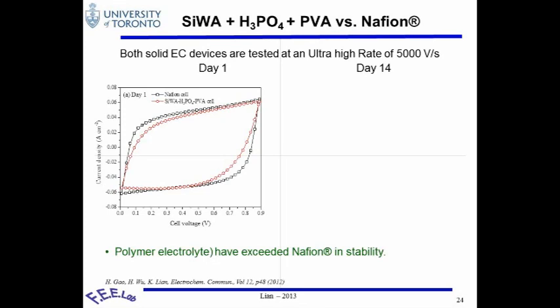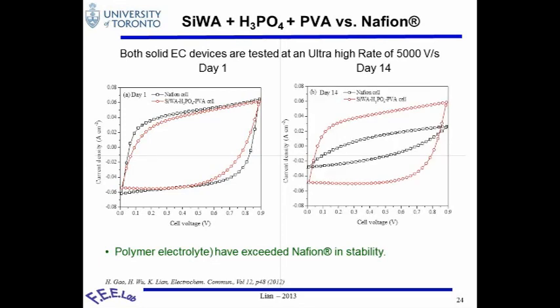The red one here is our device, our electrolyte, at day 1. At day 14, the red one still stays consistent, while the black one is the Nafion. This is consistent with the story I told you about ionic conductivity — in ambient condition, the Nafion cannot sustain the water, so the conductivity decreases significantly. This is all at a very high rate.